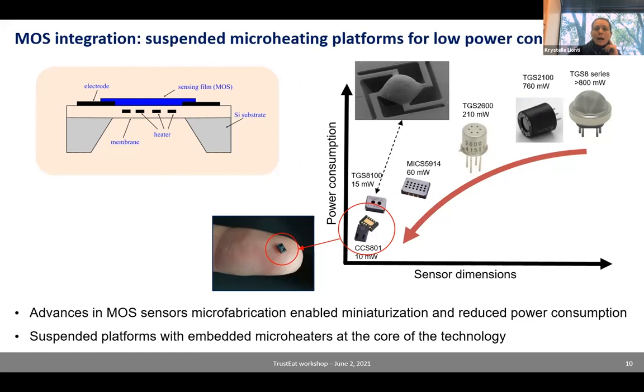And so initially, 30 years ago, the sensors were pretty large. They were pretty much heated nonstop when they were in use. Whereas nowadays, we've made a lot of progress. The footprint of the sensors is very small, and the technology to heat them up is based on a microheating platform with a suspended membrane, which is critical to minimize heat loss and be able to heat up and cool down the sensors pretty quickly. And so this is really what we wanted for our MOS materials.